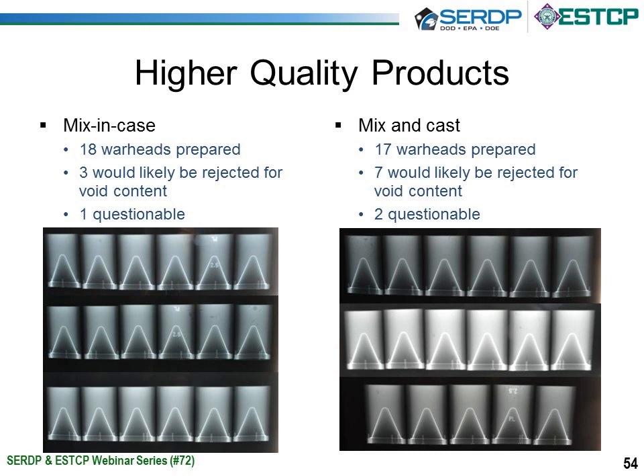If you look at these x-rays, the second bullet down there says that 7 of the warheads would likely be rejected for void content, and 2 of them are questionable. What that means basically is that we got 9 different warheads out of the 17 that we made that had air voids left in them due to this mix and then separate cast operation. If you look over on the left-hand side of your screen in the mix-in-case, we made 18 warheads, 6 different LabRAM operations to mix 3 warheads at once. There are 3 warheads, numbers 10, 11, and 12, in the middle row of all of those x-rays that would likely be rejected for void content. One of them is questionable.